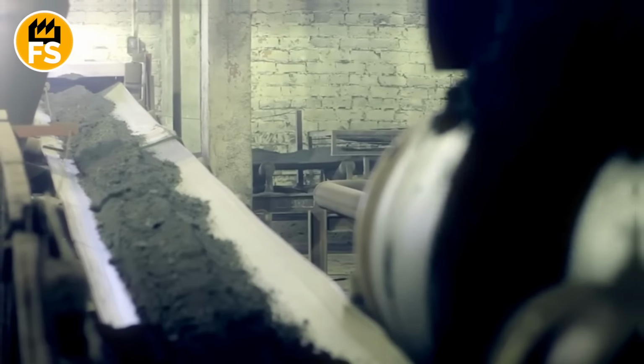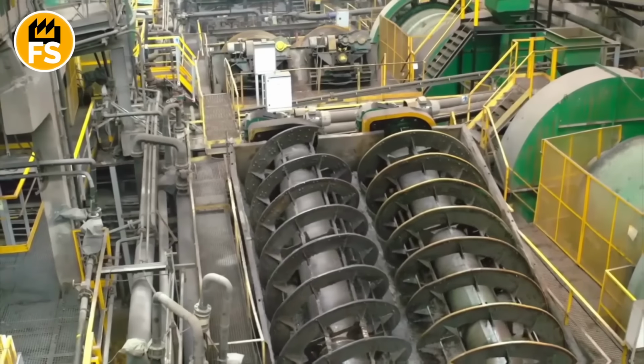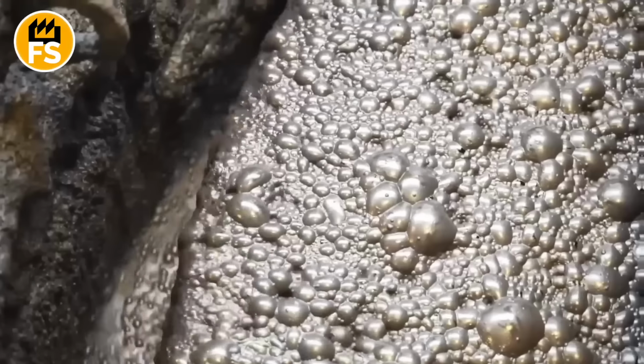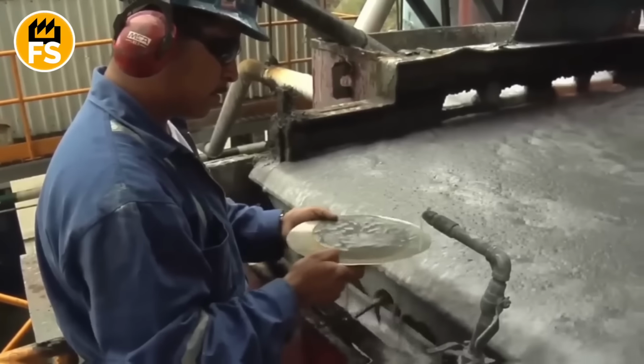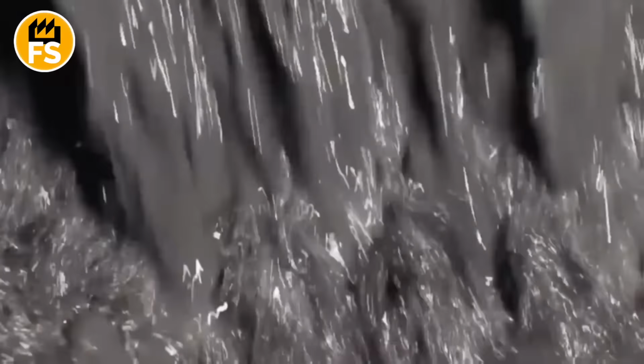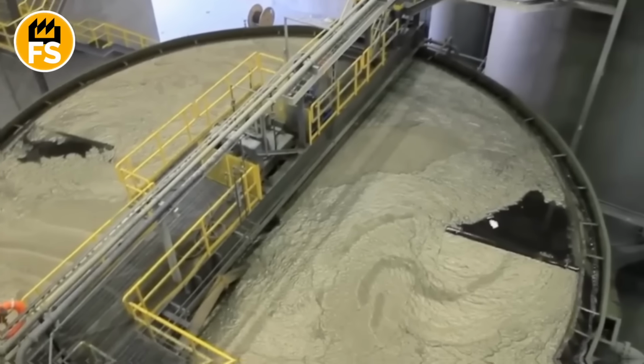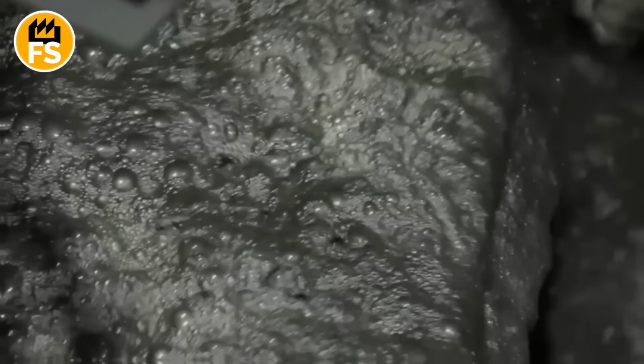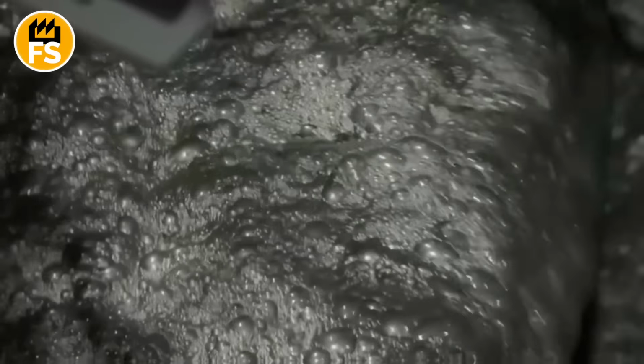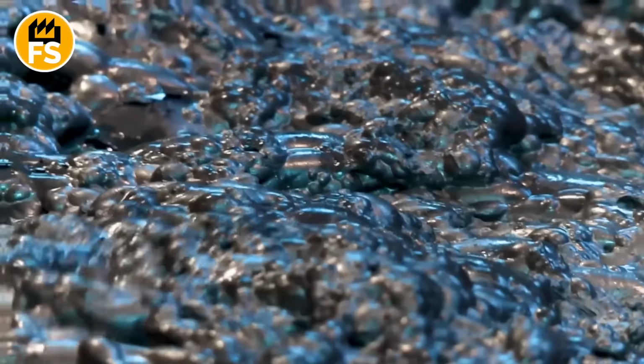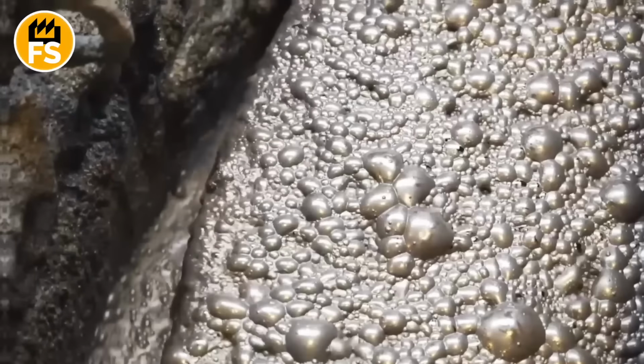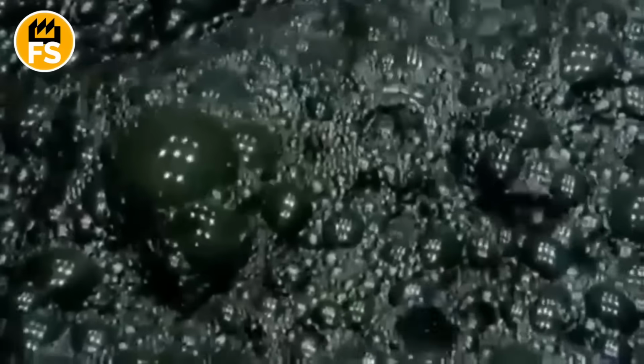The next key stage is flotation. The ground ore powder gets mixed with water and special chemical reagents in large tanks called flotation cells. These reagents selectively stick to the zinc mineral particles, making them water repellent. Then air is pumped through this mixture, creating millions of tiny bubbles. Particles of zinc mineral latch onto these bubbles and float up to the surface, creating foam. Other unwanted minerals stay at the bottom. This enriched foam is collected. That's your zinc concentrate, which can pack up to 60% zinc.